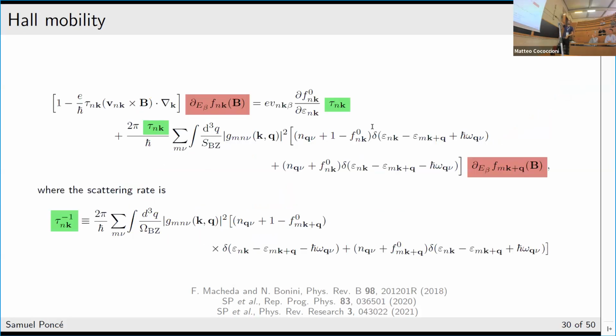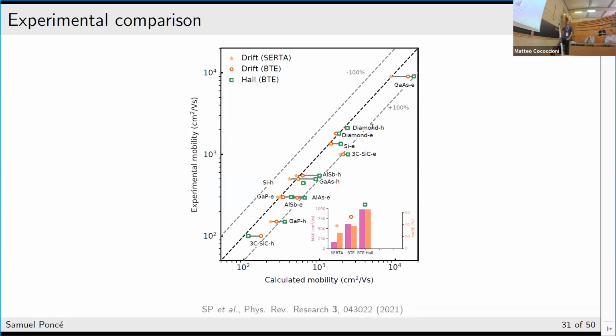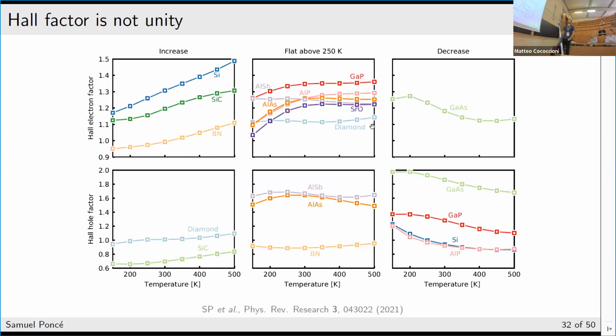What we can do is go back to our Boltzmann transport equation, and as before, on the left-hand side you have the normal term, and then you have an additional term due to this additional driving term, which is simply the magnetic field. We compute this at a finite small magnetic field, and then we can solve again this Boltzmann transport equation, but now including the magnetic field. If you do that, you obtain what is called the Hall Boltzmann transport equation. You can see that in this case we are overestimating all the time, up to a factor 2. So we are somewhat predictive, but we are always overestimating, which is what is expected.